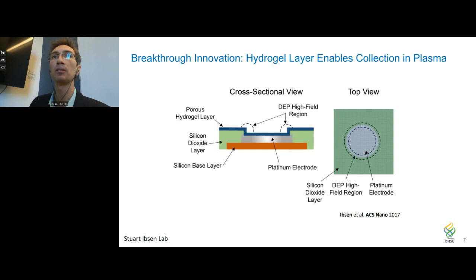But the addition of this hydrogel layer creates a physical barrier between the platinum and the plasma sample above. And that suppresses a lot of this electrochemistry. So we can actually run dielectrophoresis and collect particles in undiluted plasma, which is truly unique in the electrokinetic field, where most of the work has to be in diluted plasma or in special buffers to prevent this kind of electrolysis. So this is really a big advance in the field, to be able to work directly with undiluted plasma.